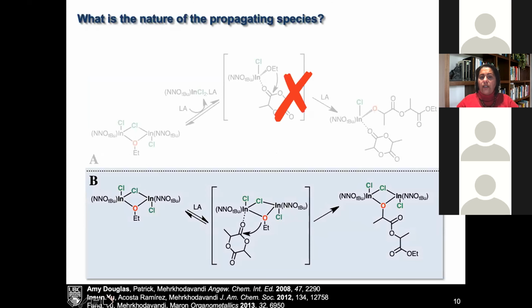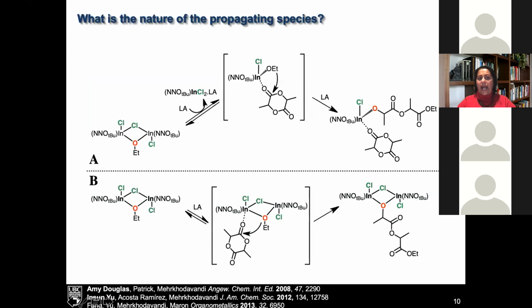The reason these systems work so well is that there are two possible mechanisms for lactide polymerization. You have a Lewis acidic metal center, and in both mechanisms, the lactide can coordinate to the Lewis acidic metal. The ketone here gets activated, and then a coordinated alkoxide will attack this activated carbonyl, leading to a ring opening event. The question that we came across was, we start from a dinuclear indium system. Does it break apart to a mononuclear system, or does it stay as an aggregate? And overwhelming evidence, both experimental and theoretical, has shown that in fact we stay as a dinuclear system.